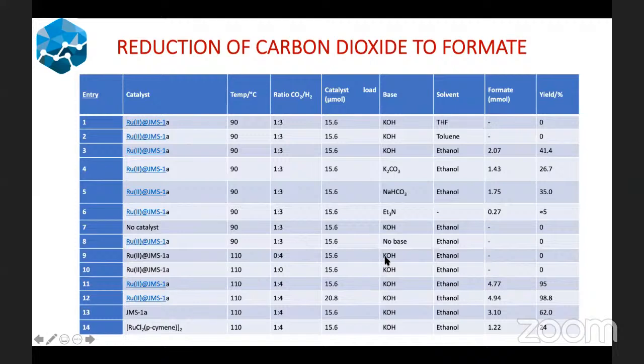And then in entry number 9, in the absence of carbon dioxide, no product is also observed. So this actually confirms that the source of carbon from the formate that we are forming is actually carbon dioxide, because in entry number 9, you can clearly see that there is no carbon dioxide that was used. We only used the hydrogen, and of course, no product was also observed. And of course, the same also applies if you don't have hydrogen, you also don't get your product.